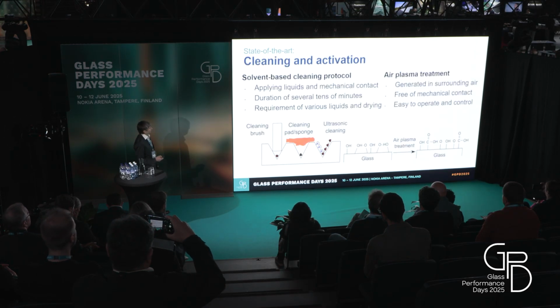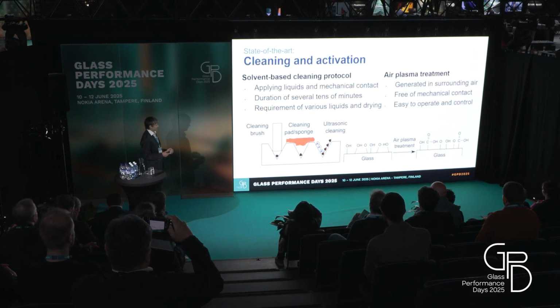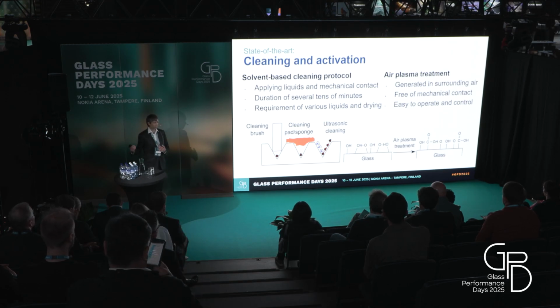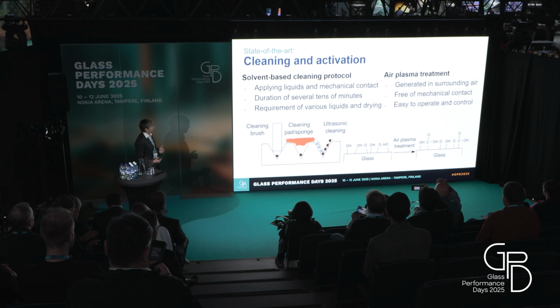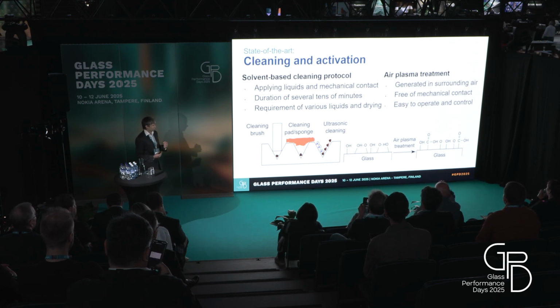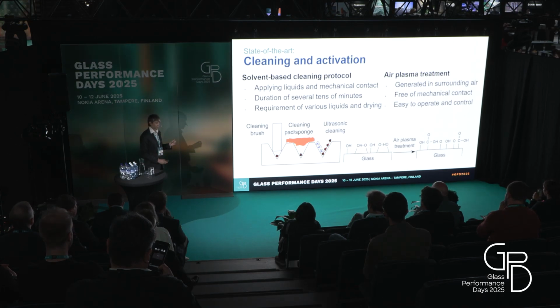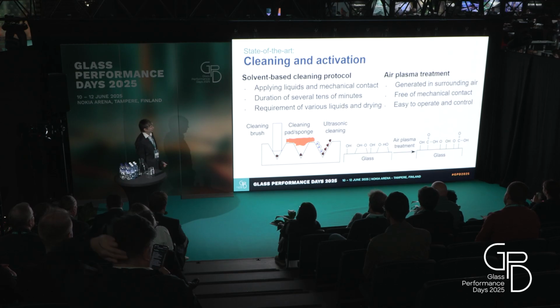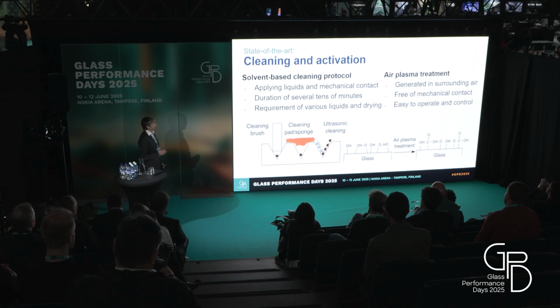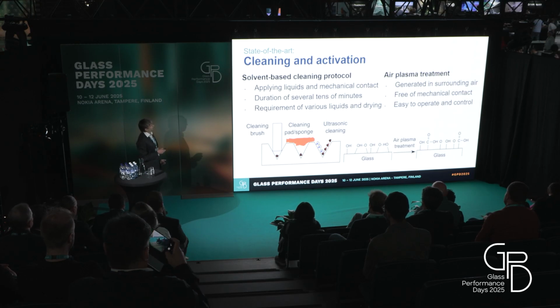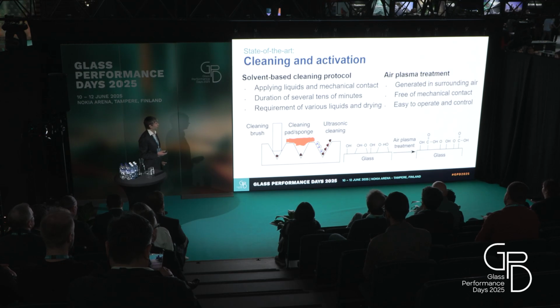And so typically cleaning techniques use some solvents or mechanical brushes or ultrasonic cleaning, and they have some limitations. For example, if you want to clean a very fragile material, I worked with a flexible glass which was just 30 microns thin, so it was fragile, and a non-contact method for its cleaning was something challenging, to overcome these problems which come from the solvent-based cleaning protocol.